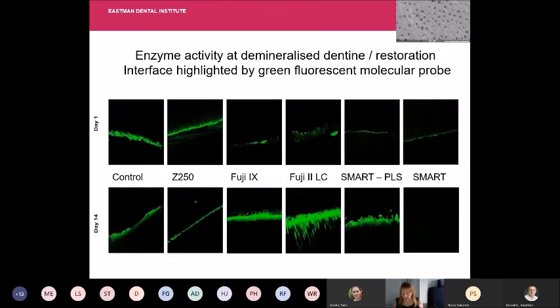Additionally, we've used this dentine model to look at how enzymes are working on the surface, on the interface between the demineralized dentine and the composite. So we've taken demineralized dentine, we've added a probe that fluoresces green when the enzymes are being active. We've then restored the top surface, left it incubating for either a day or for 14 days, and then sliced through the restoration to have a look at that interface, to see if the enzymes are actually active.